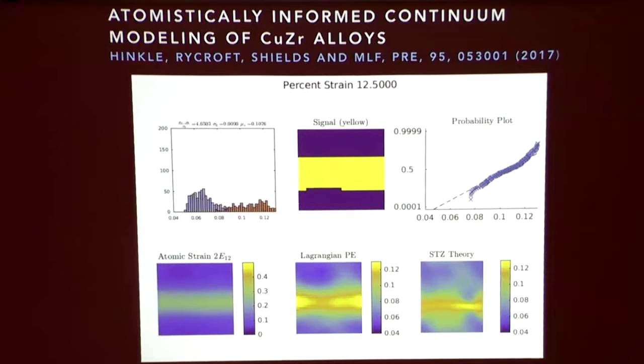The two regions separate. So you have the material inside the shear band, the material outside the shear band, and here you see the strain is localized. The potential energy per atom is significantly higher inside the shear band than outside the shear band. And then the theory predicts also localization at nearly the same location.